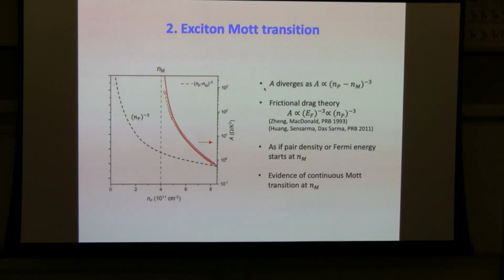Yes, Mott thinks that it's first order because he thinks that the screening on the two sides are very different. That's how he estimated the critical density. But what is the mobility difference between the electron and hole channel here? Like in these densities? They have nearly the same turn-on density in the two cases, but the electron mass is about double of the hole mass. So the mobility may be a factor of 2.